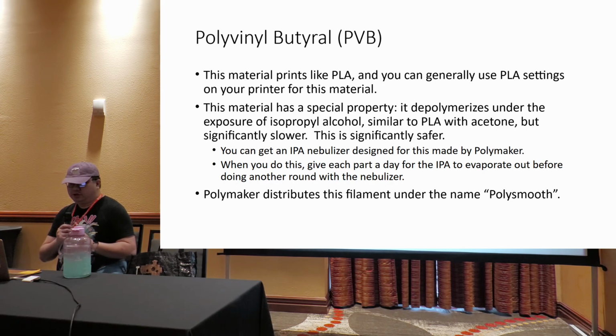This particular material is very good for one thing. You can actually spritz it or nebulize the part with isopropyl alcohol, and it will basically smooth it for you. You do not need XTC-3D. You don't need to use really toxic acetone. You just need isopropyl alcohol. And one of the companies that sells this, Polymaker, actually makes a special nebulizer that costs about $100, but it is well worth the cost.